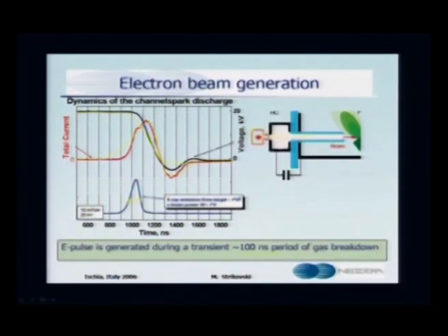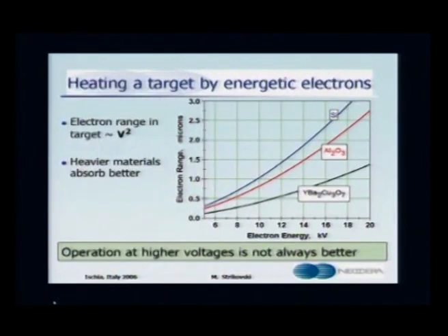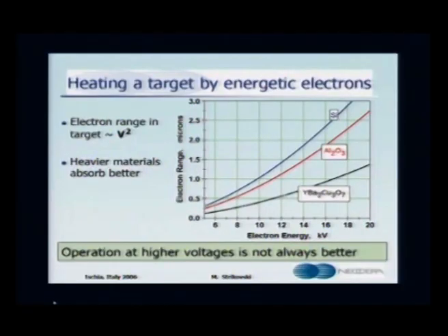So you have a very narrow range where this pulse width is, of the order of 100 nanoseconds, and this is of prime importance for the PED process, where you have an electron pulse which has a very sharp breakdown, and the pulse width is as close as 100 nanoseconds. So with this pulse it is possible to bring about many changes when the electron beam is hitting the target surface. Therefore, when such a high energy pulse is hitting the target, now you can look at how the materials get ablated.